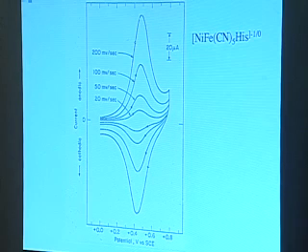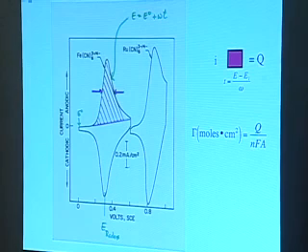And it was pointed out that since you have a lattice on the surface, a crystalline lattice, you could very well believe that one molecule changing would affect the others. That is, there are nearest neighbor interactions. I pointed out to you that on this prior scheme, that actually is 90 millivolts right there, which means there's either no nearest neighbor interactions, or that the attractive and repulsive interactions exactly cancel out. And me, being a naive electrochemist, figured 90 millivolts, Occam's razor, no interactions. And you, being sophisticated chemists, told me you're out of your mind, it's a lattice. Of course the interactions cancel out, and you're right.